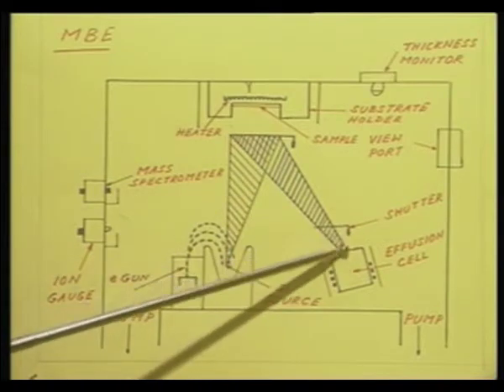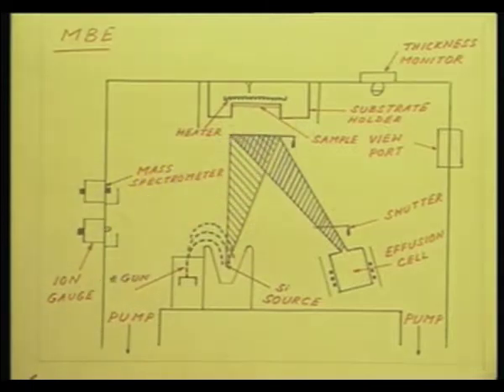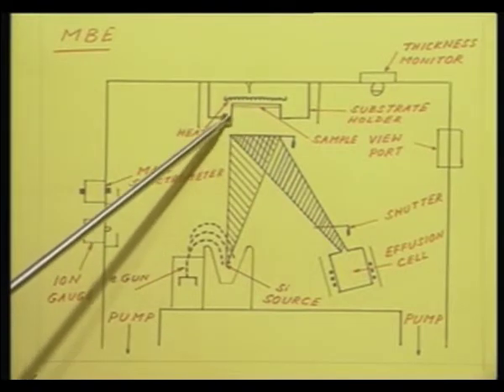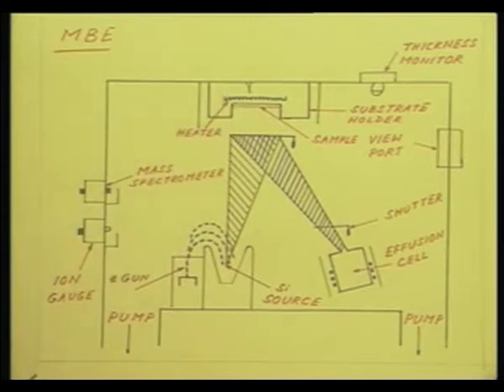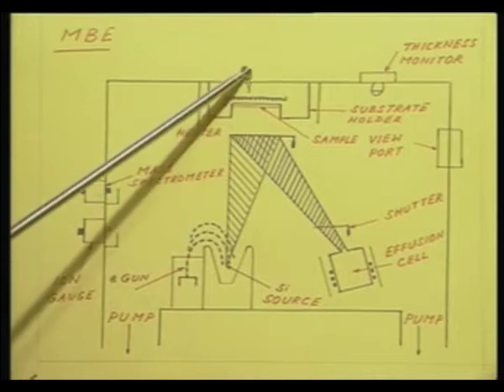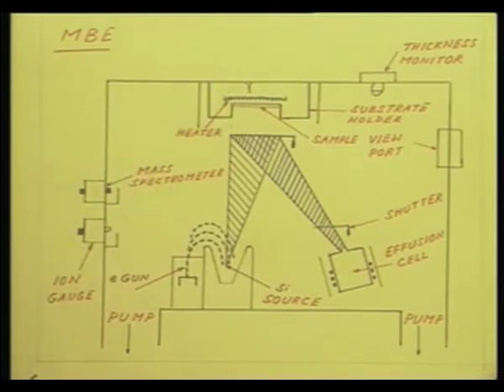You have one or more than one shutters. These shutters are usually controlled by microprocessors, that is to control the layer thickness as well as the amount of dopants incorporated in the epitaxial layer that is grown. The sample itself is placed here. There is a substrate holder, there is a small heater, there is a thermocouple to measure the temperature of the substrate. The substrate temperature is usually much lower, around 400 to 800 degrees centigrade.